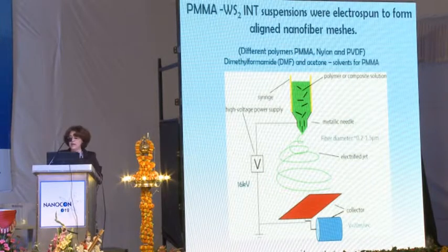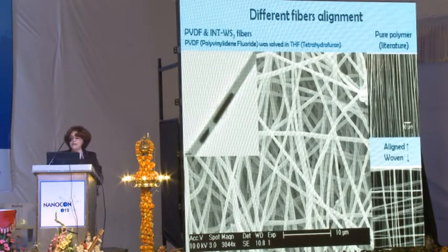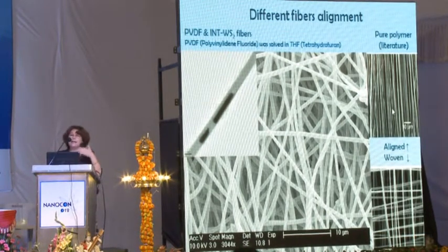The solvent evaporates and you have solid fibers, and the nanotubes are inside and aligned due to this setup. You can see the diameters of fibers which could be obtained, 0.2 to 1.5 micron, and different collectors where you can gather this material. One example you can see here is the same image of fibers made from PVDF polymer. Here is the TEM picture where you see one fiber with a nanotube inside. This technique aligns these nanotubes, and when you collect the fibers in the correct way, you can also align the fibers, and in this way align the nanotubes.